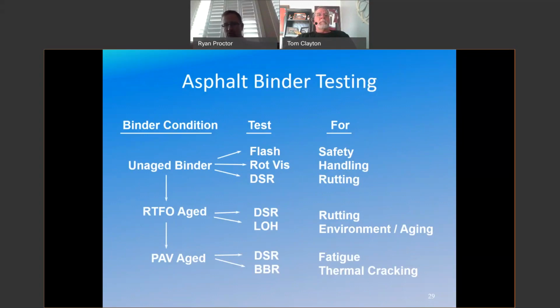When that happens, you're more likely to see smoking issues or odor issues, and it could even be a safety issue. The loss on heating test and the flash point, I would say for the vast majority of the time, have eliminated those issues. But it is important that those tests stay on a specification.